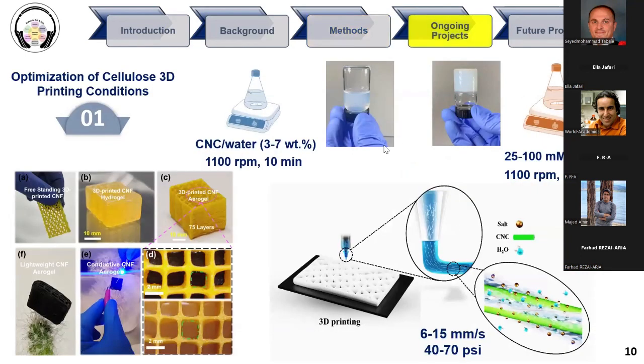In terms of macro scale, which is actually related to this meeting, we need to optimize the 3D printing conditions first. In one of my first works, I tried to optimize the cellulose 3D printing conditions. As you can see here, if we have just cellulose, and if we tilt the vial, it can easily flow. And when our ink just flows, it's not a good candidate for extrusion 3D printing, and I'll tell you why. Because we need a highly viscous material. Just for example, imagine we use 3, 5, and 7 weight percentage of cellulose, and whenever we tilt our vial, all samples flow. As I told you, these samples are not good for us.